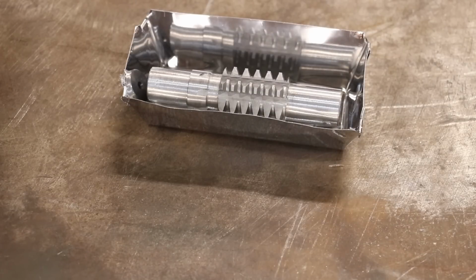mixture. The brine is going to boil at a little bit higher temperature than regular water, and that's the ideal temperature for this W1 drill rod. Once we quench it, we're going to put it back in the oven, but at a lower temperature. We're going to drop the oven temperature down to 400 degrees Fahrenheit, and we'll soak it for 2 hours at that, and that will actually temper it to get the hardness exactly where you want it, and then we'll just let it air cool to room temperature after that.